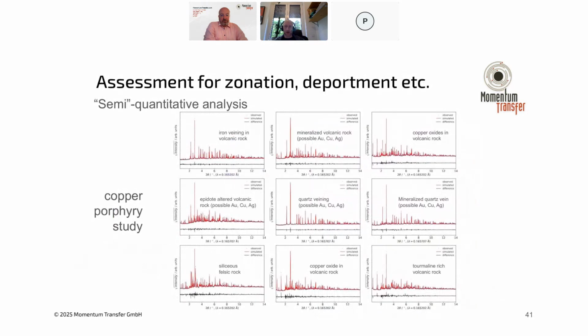There are other methods that you can use to do that with varying accuracies in different cases. So there's also external calibration methods, where you use other measured reference materials to add directly into the refinement. And it depends on what kind of system you're working with. But the internal calibration method is generally what we use and is working very well in most cases.